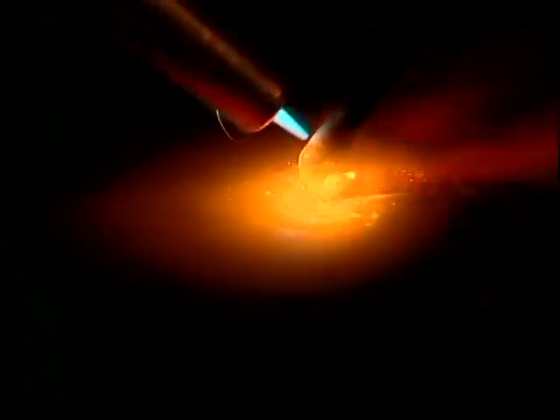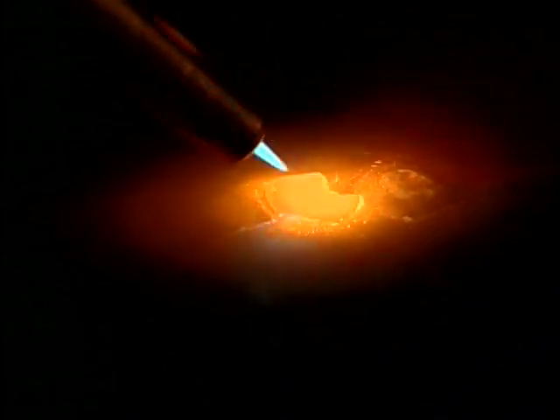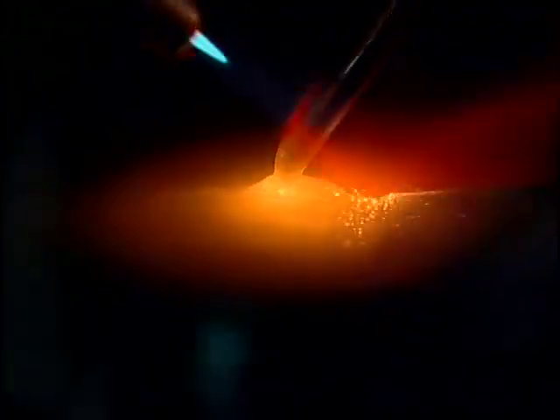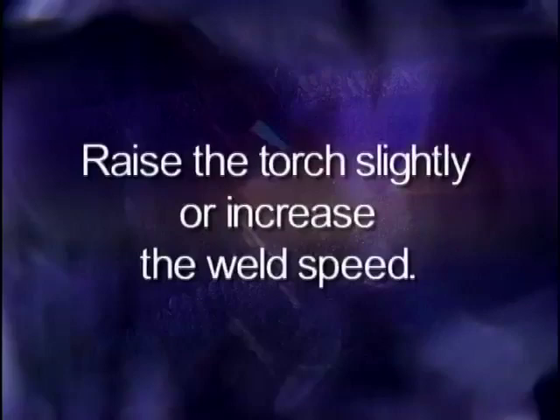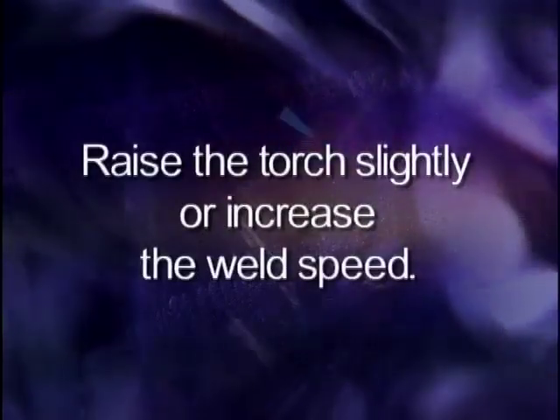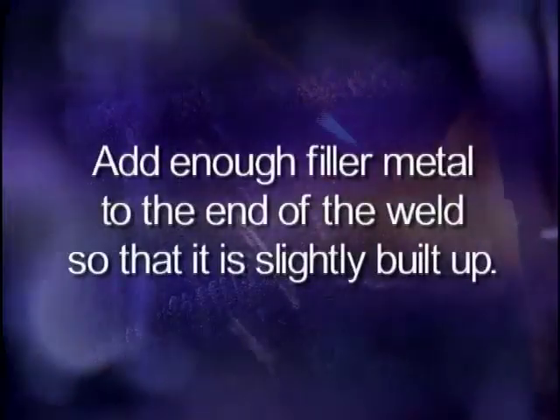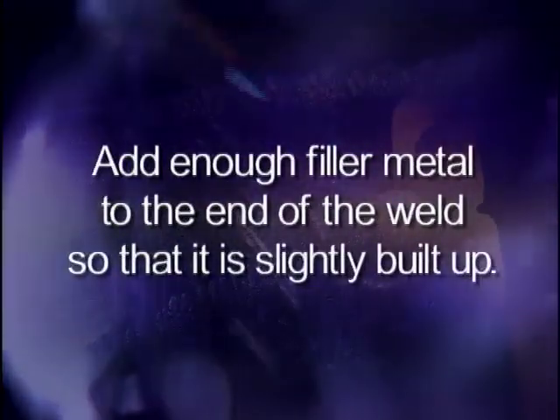When the weld reaches the opposite end of the plate, it will tend to become larger because there is less surrounding metal to absorb the heat of the torch. To prevent the weld from increasing in size, raise the torch slightly or increase the weld speed. Add enough filler metal to the end of the weld so that it is slightly built up. This will help prevent crater cracking as the weld cools.